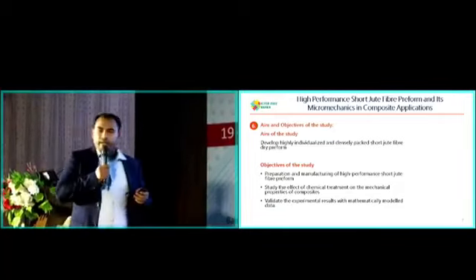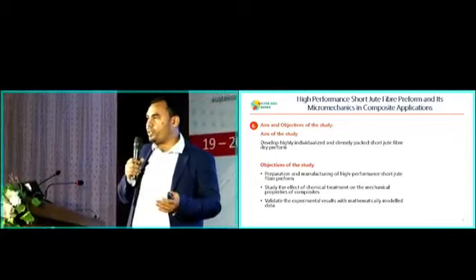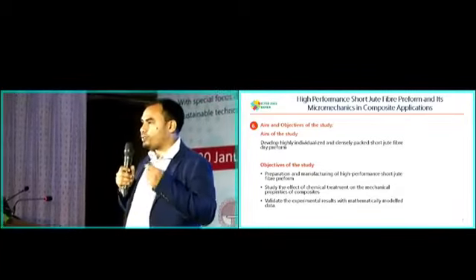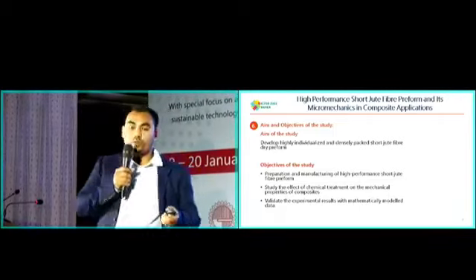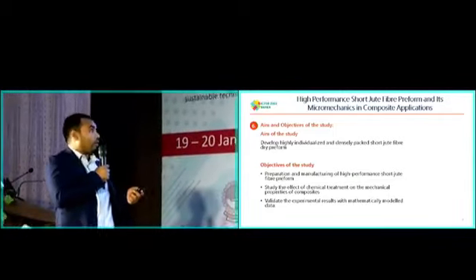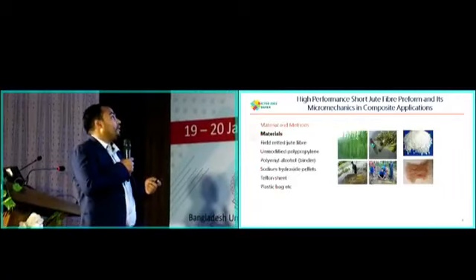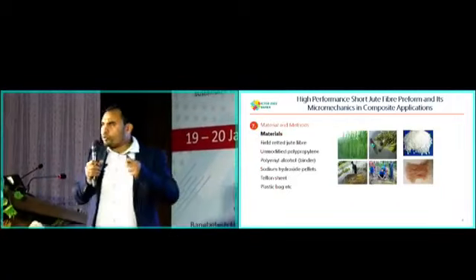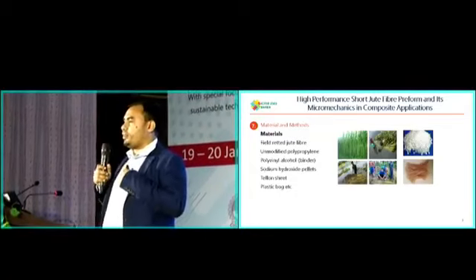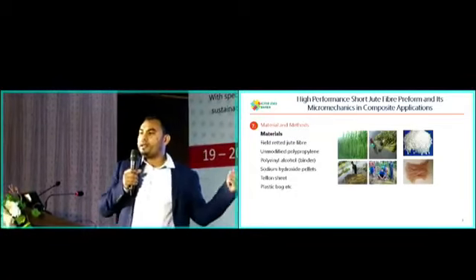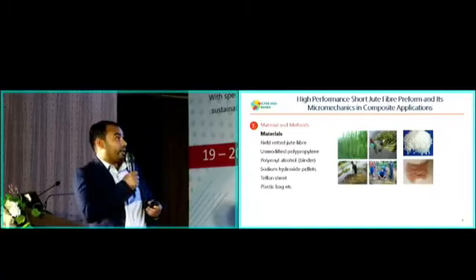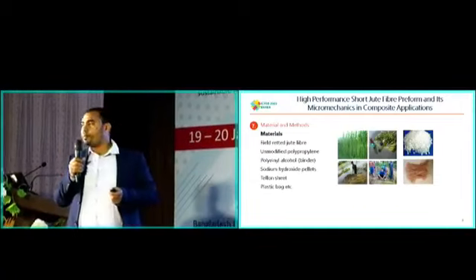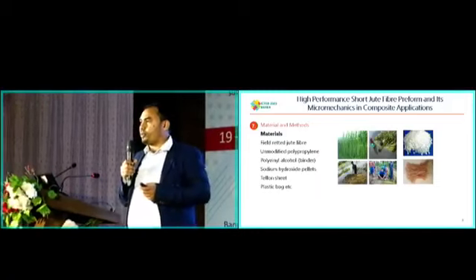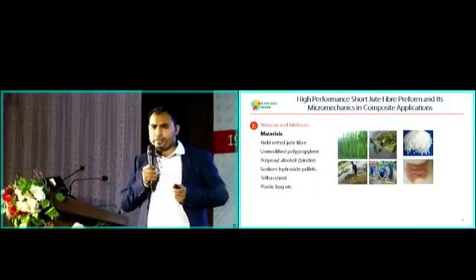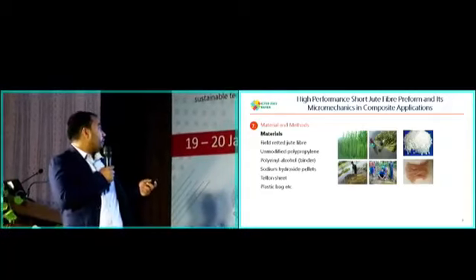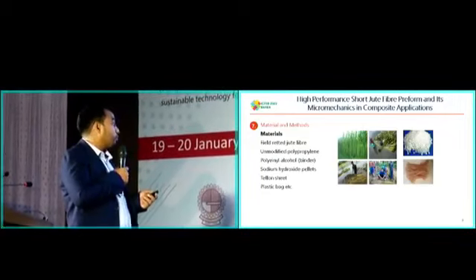It is also very important to validate the experimental data with mathematical model data, to see whether the model fits the experimental data or not. So we also adopted this model for checking the validity of the composites. The main raw material was collected by myself; I cultivated the jute in my area and also collected the fibers, and we chose polypropylene as the matrix in this project, and there are some other auxiliaries used for the manufacturing of the composites.